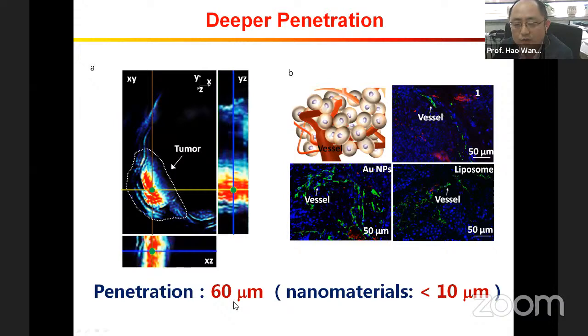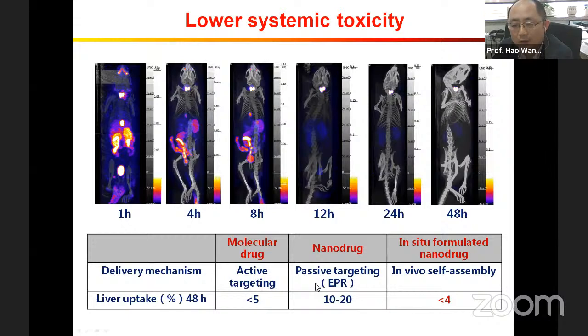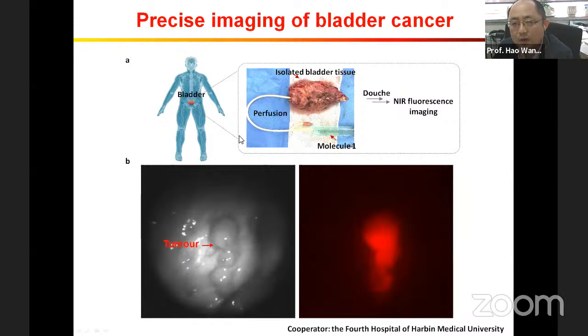In our case, the penetration distance is around 60 micrometers. It also shows lower systemic toxicity, because the non-self-assembled small molecule peptide is easily cleared through the kidney. You can see that in this case, the liver retention uptake at 48 hours after administration is less than 4%. So it's quite safe.